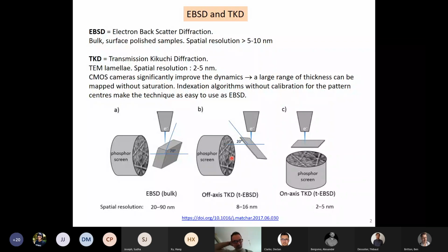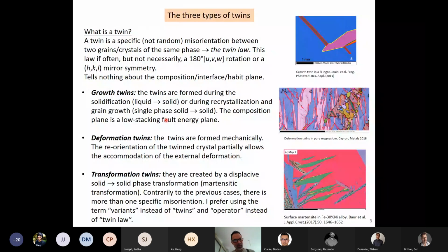So let me now define what I call twins. It's a very, very broad term that can sometimes be confusing. If I take the very large definition, a twin is a specific, by specific I mean non-random, misorientation between two grains or two crystals of the same phase. And crystallographers call that a twin law. This law is often a rotation of 180 degrees around a crystallographic direction, or it can also be a mirror symmetry through a crystallographic plane. And you can look in this definition.